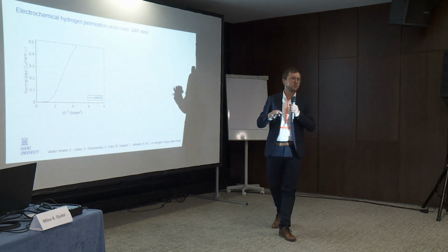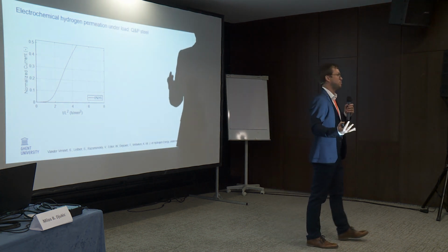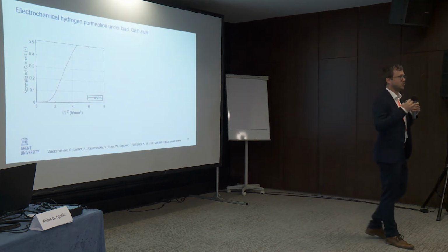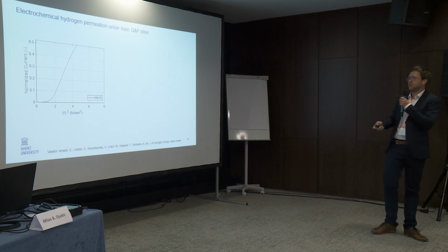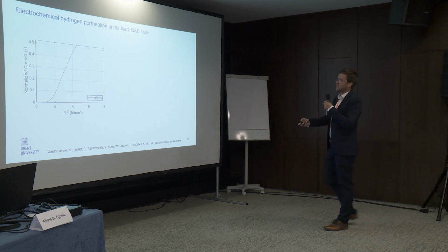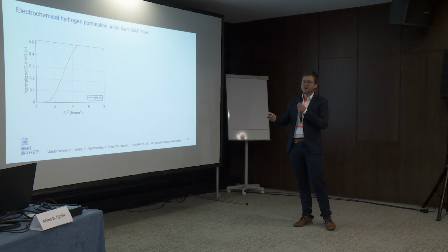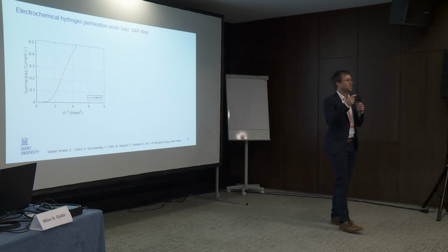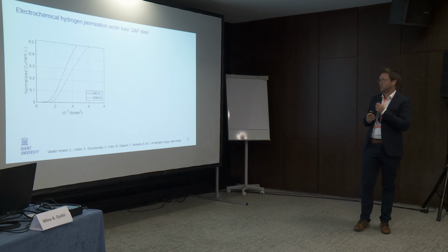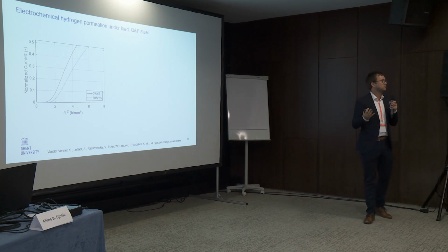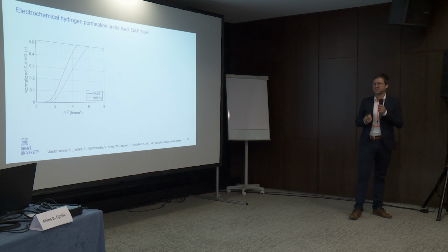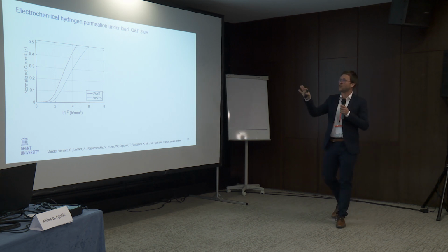Let's now go to QMP because we want to evaluate if retained austenite can trap. We don't know yet, because with just charging, we don't see a high temperature peak. So at 0% of the yield strength, we have this permeation transient. Now with elastic load in dual phase, we have an accelerated diffusion, right? With QMP, we slow down diffusion. Quite strange, the opposite as in the dual phase steel. So let's continue. Is this now an error or not?